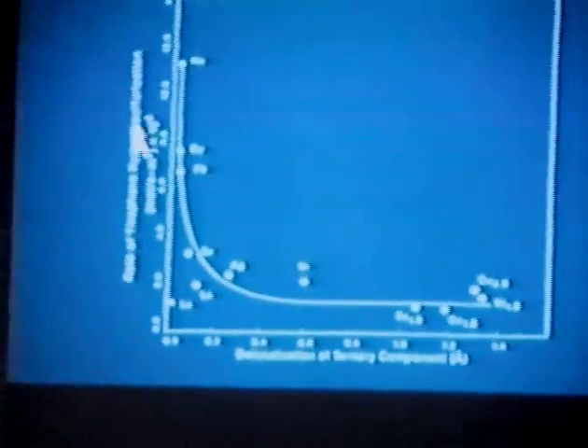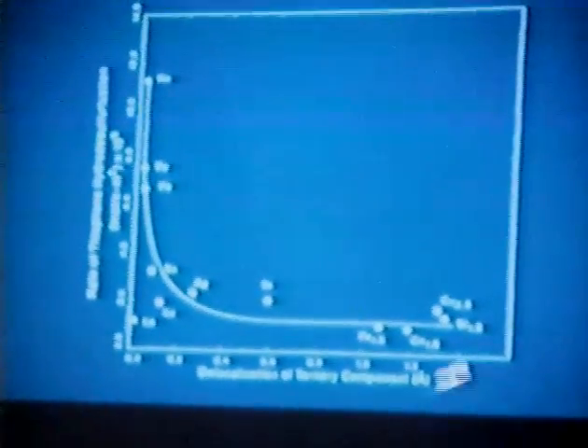You can see this structurally, or you can see this very clearly when you start to make a plot of, for example, the rate of thiophene hydrodesulfurization versus this delocalization. Here are all these small cations that can move through the structure, and at least in one case here with the cobalt compound, we've been able to see this cobalt material retreating down into the bulk of the catalyst and some formation of MoS2. But the most active materials are also the most stable materials.